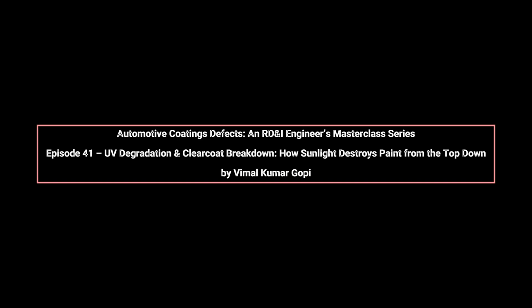From a troubleshooting standpoint, UV degradation appears as uniform gloss loss on horizontal surfaces, fading of color depth, microcracking under magnification, and chalky residues after washing. Distinguishing UV-driven failure from chemical etching or abrasion requires careful analysis of exposure patterns and surface chemistry.